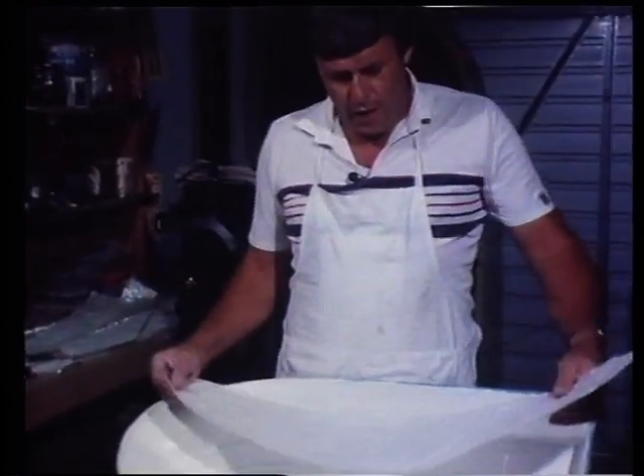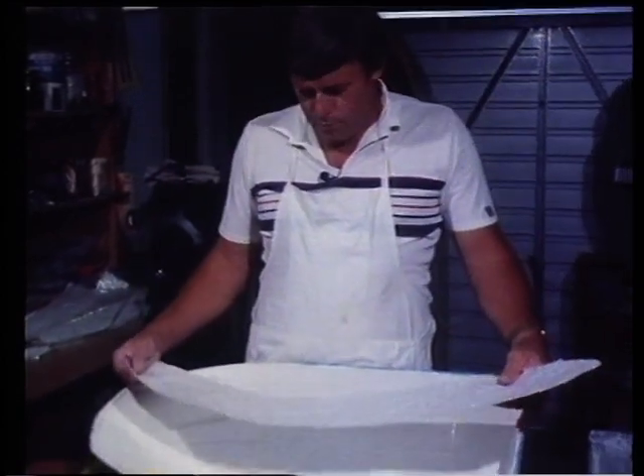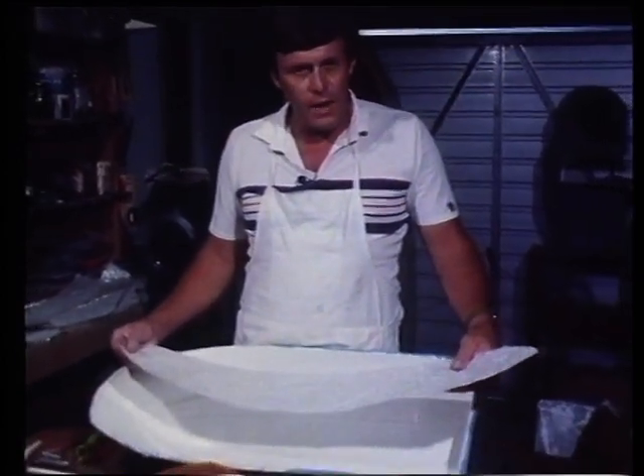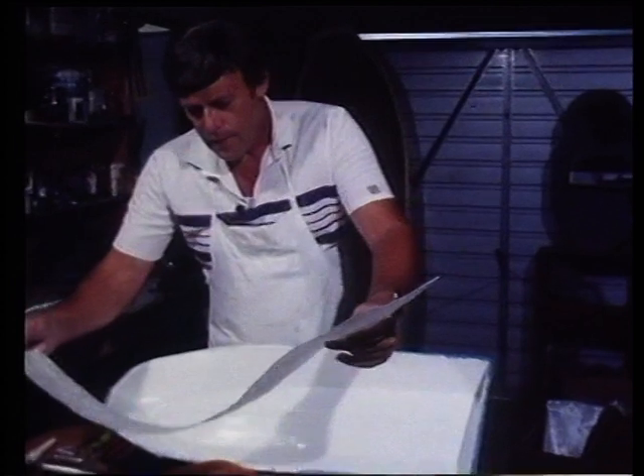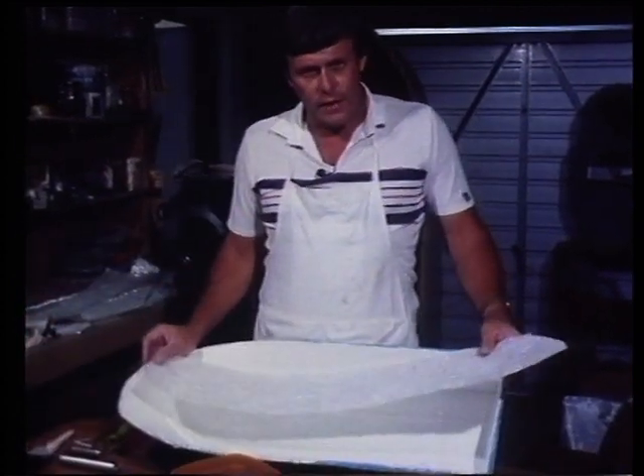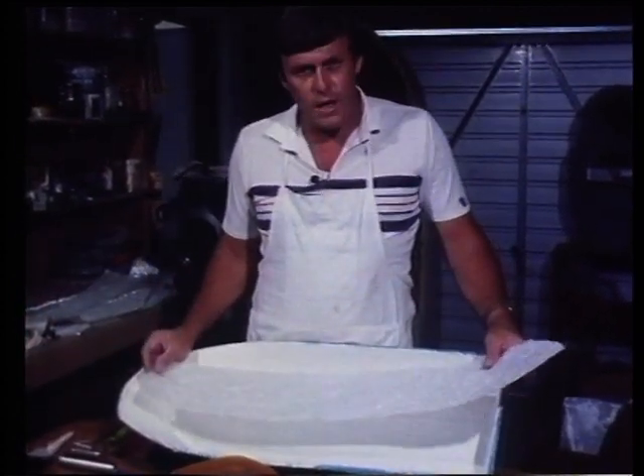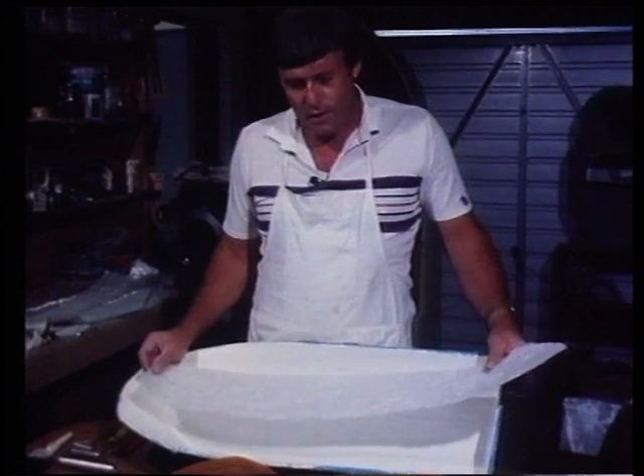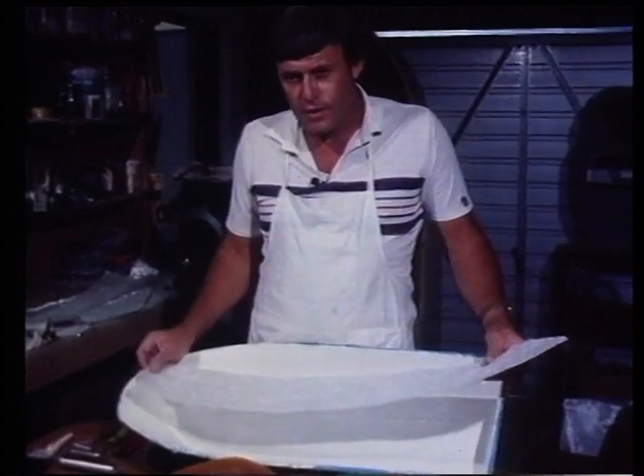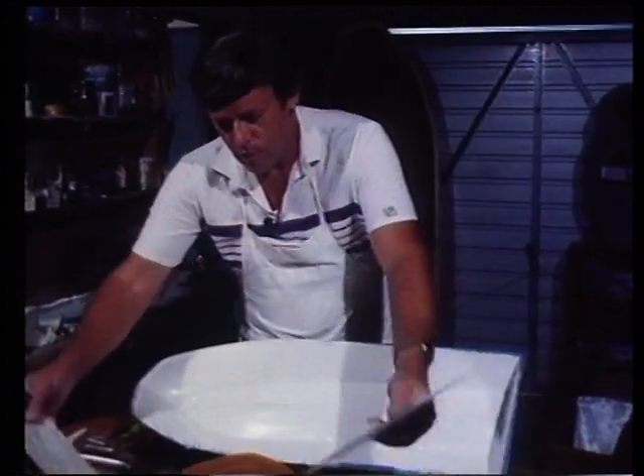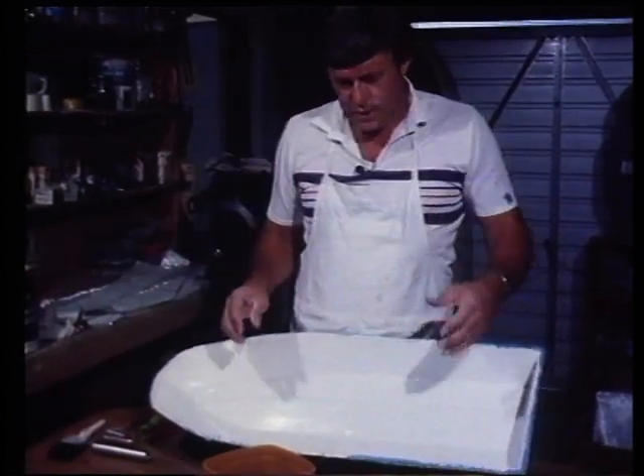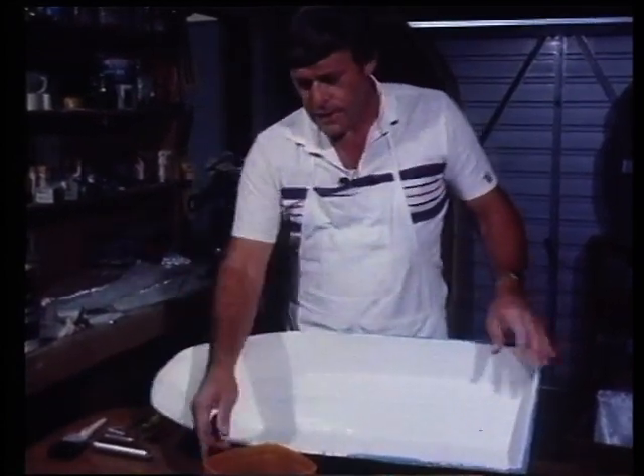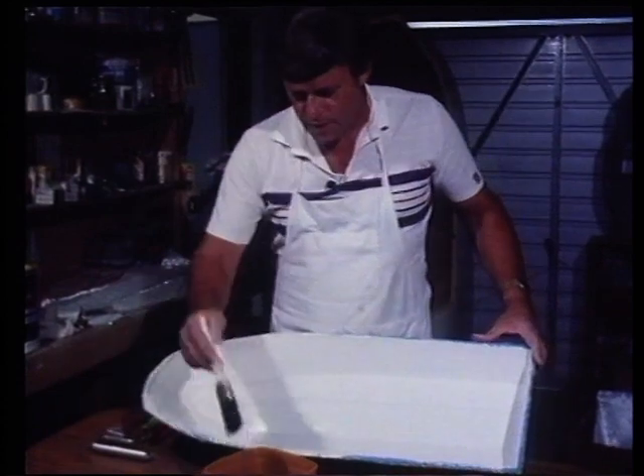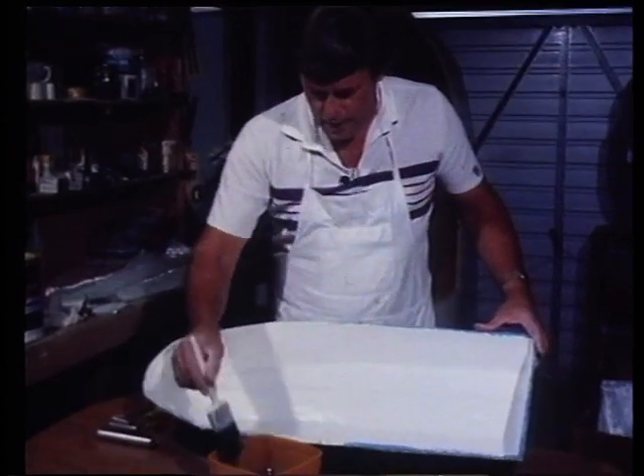You could put the fiberglass in and just slap great brushfuls of resin all over it and you would impregnate it, but the resin and the glass work together in a fairly definite ratio to give you the maximum strength in the laminate, and that ratio is around about 2 to 1 by weight. So in order to achieve that ratio, or get as close as you possibly can to it, it's necessary to use a couple of special techniques. Now, I'll just show you how that's done.